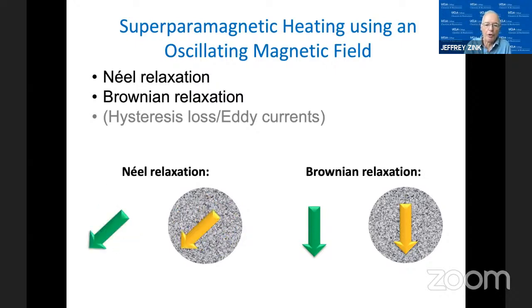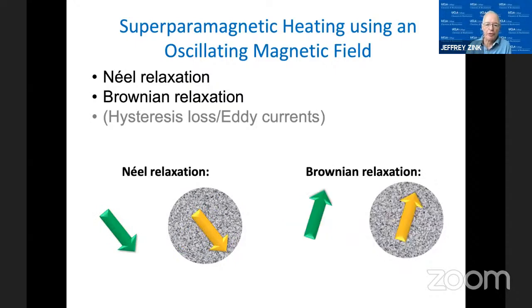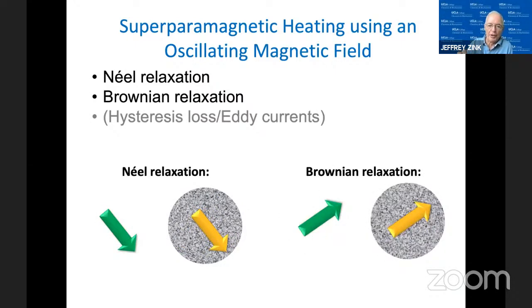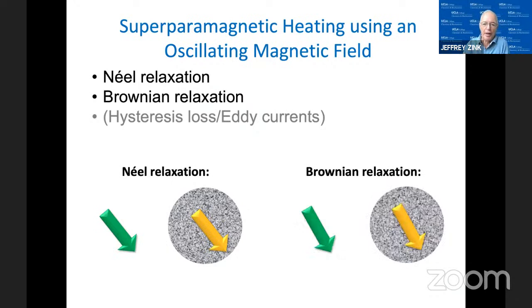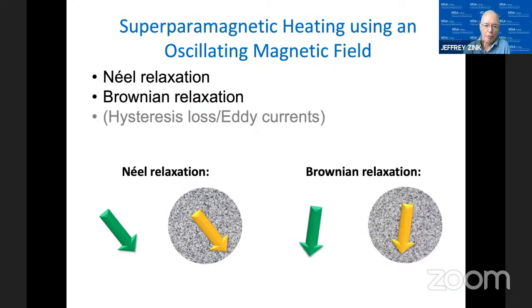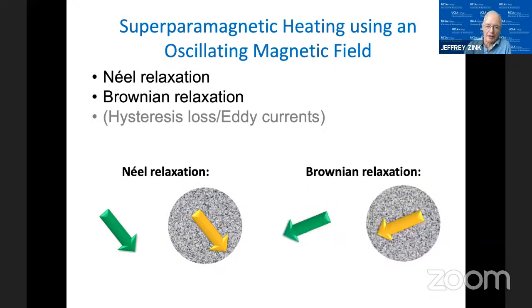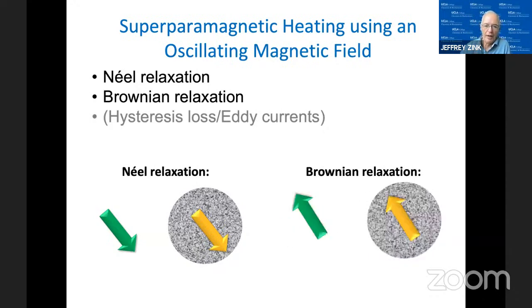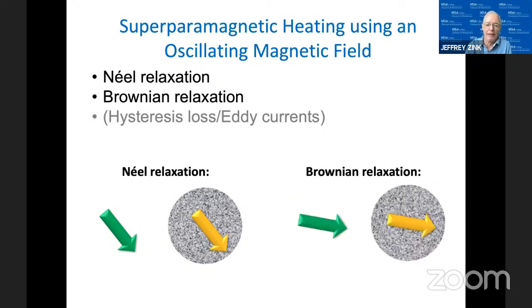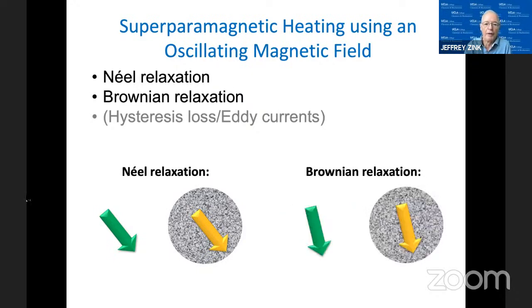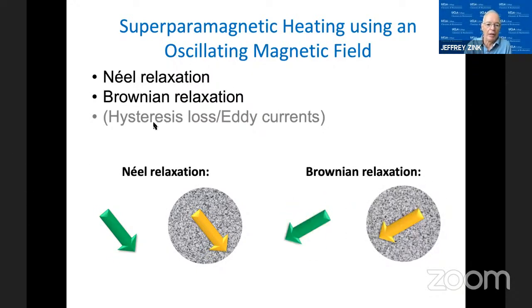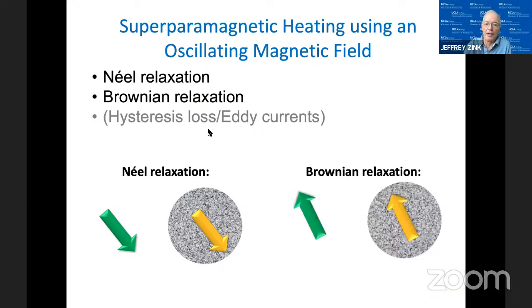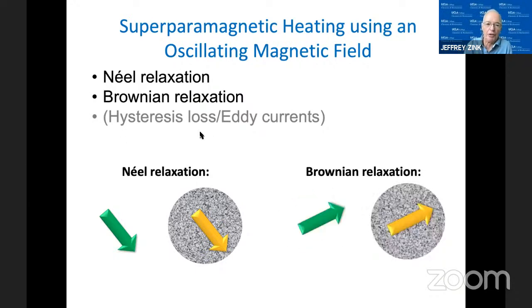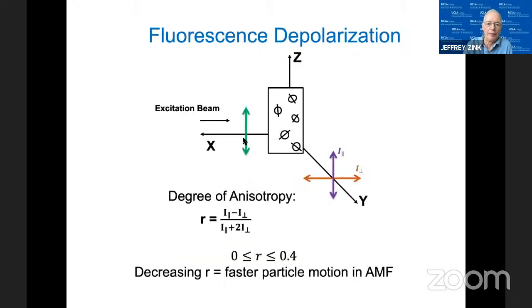The second one is what's called Brownian relaxation. In this particular case, the spins are locked into the crystal structure and the entire structure moves. So it's more like a frictional heating. It's the motion of the particle itself. And that's called Brownian relaxation, the second mechanism that can operate. In macroscopic systems, hysteresis-induced electrical currents, eddy currents, cause heating. That's commonly used in industry for heating big pieces of metal, but it's not relevant to the system that we're using here.